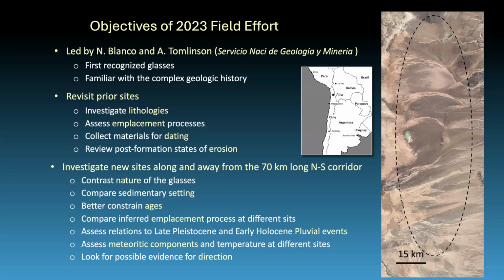So anyway, on the right-hand side is the impact ellipse, an ellipse that contains all the glass fields that they've found so far. It's still about 75 kilometers long, but now it's much wider. And that is the issue for the interpretation I presented 3 years ago. What I proposed was that it was a very shallow, oblique impact, and it started fragmenting in the upper atmosphere, and then it fragmented into pieces of different sizes. The bigger pieces continued downrange. The smaller pieces dropped out earlier and exploded before they hit the ground. And that is one way you could get a long chain.